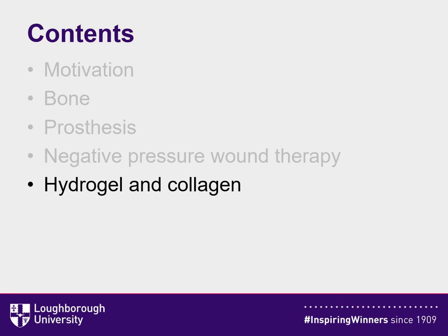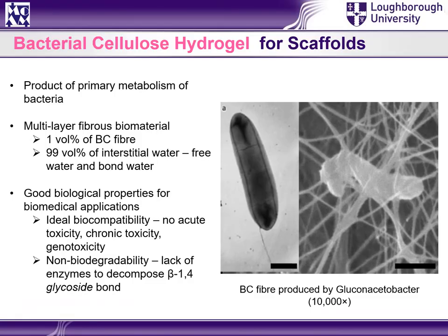Now I would move to the next topic: materials which are biological, but which have a potential to be used for biomedical applications, hydrogels and collagen. The hydrogel material is an interesting one. It is not only that it is produced by bacteria, forming a nanofiber network. The most important part of this material is that it contains 99% water. So you can imagine this is a composite with nanofibers, but instead of a polymeric matrix, it has water. Clearly, this would affect its performance in a significant way.